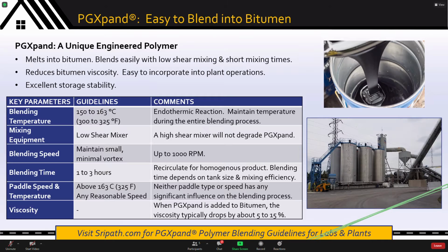It is fairly user friendly. Typical mixing times, depending on whether you have recirculation in your tank or not, can be anywhere from 1 to 3 hours before it's completely ready. And as I noted to you before, while it is added to the bitumen, PGXpand will help with the operations because it helps to lower viscosity, unlike other conventional polymers that are used for polymer modification.